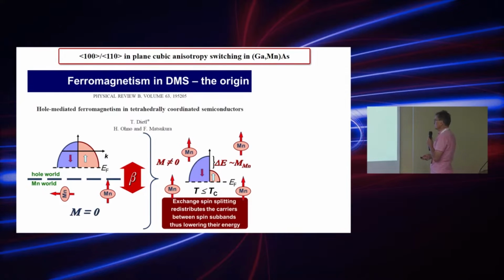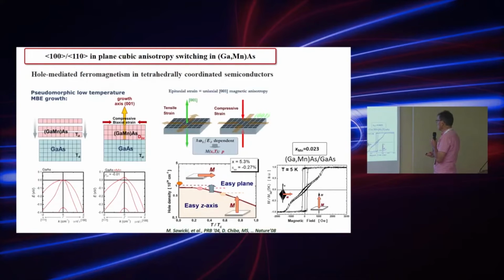So the highest temperature at which this energy gain in holes overcompensates the penalty of entropy by the manganese atoms is the Curie temperature for this system. And actually, it is the interaction between the holes and manganese which is responsible for the very rich magnetic properties of this system. So gallium manganese arsenide is grown basically exclusively